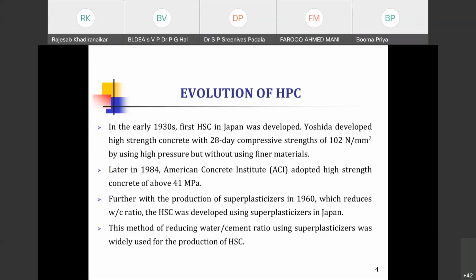And further, with the production of super plasticizers in the 1960s, we were able to reduce the water cement ratio substantially. And HSC was developed using super plasticizers in Japan. This method of reducing water cement ratio using a super plasticizer was widely used for the production of high strength concrete, since at the beginning most of us were designing the concrete mix based on the strength, and they were able to get increased strength, and they called it high strength. And at that point of time, they were not very much worried about the performance characteristics of the concrete they had produced. And they got the increase in strength, and they rightly called it high strength concrete.